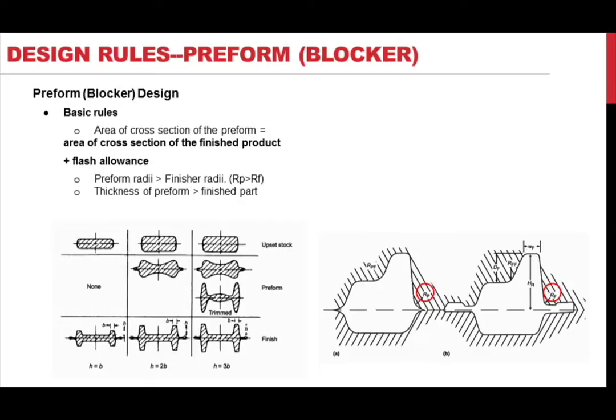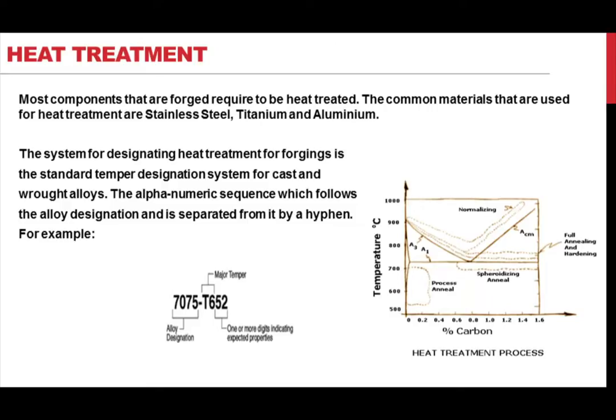Also, for different heights of ribs, different numbers of preforms are used, and again, this may require time for experimental trial and error. Heat treating is often employed to develop properties in the forging that could not otherwise be realized with the selected alloy. Although it is most often associated with ferrous alloys, forging alloys in all of the 7 major alloy groups can be heat treated to advantage.